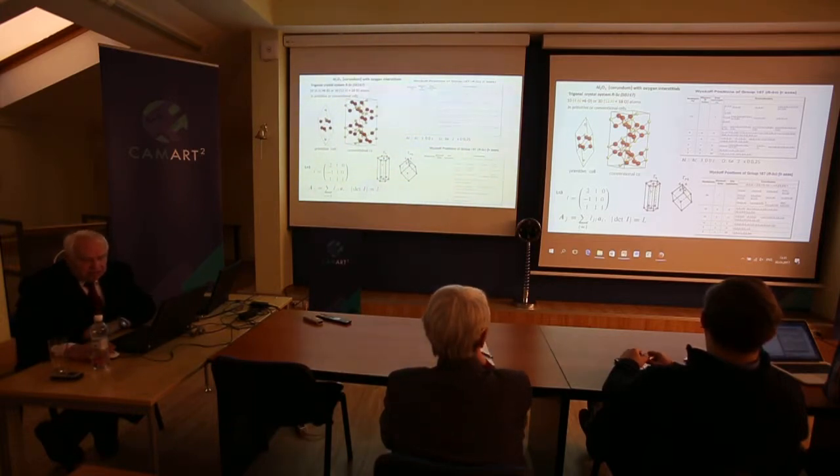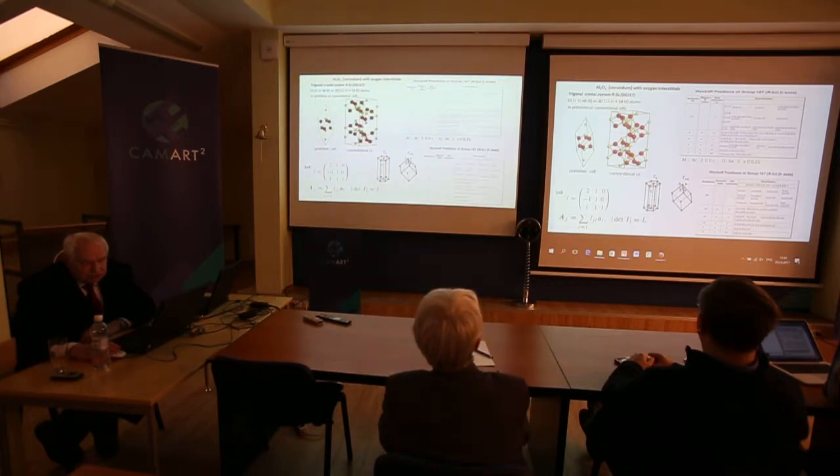How are these settings connected? With a translation: the rhombohedral primitive lattice translation vectors are transformed with this matrix. The determinant of it is 3, so the conventional unit cell, you can call it a supercell, is 3 times larger than the primitive. It consists of 30 atoms, 12 aluminium and 18 oxygen. This is conventional, this is primitive.